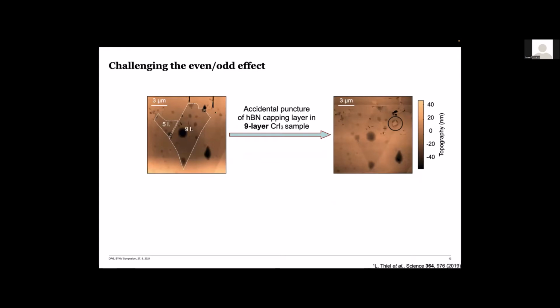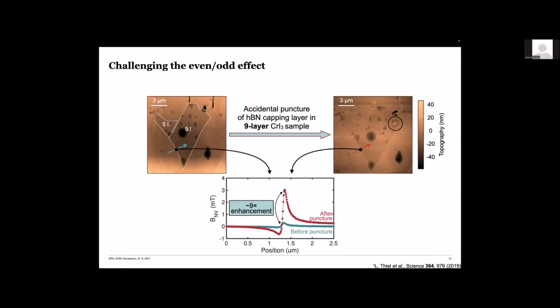So here you see an AFM scan of one of the samples that we looked at. In this case, it was a 5-layer sample and a 9-layer sample next to each other. And one night, late at night, my student Lucas was scanning the sample and accidentally crashed the tip into the sample. And you see here this type of destruction that this caused. And initially, we were quite disappointed. We thought this would essentially destroy the sample and stop the measurement run. But that was not the case.